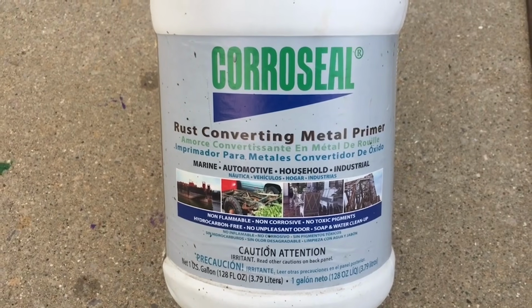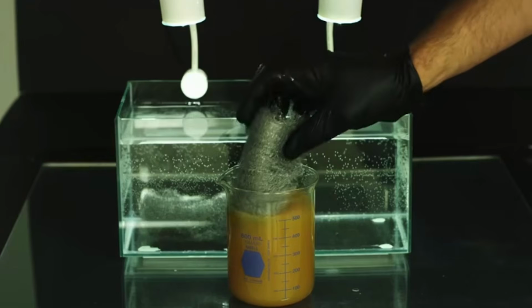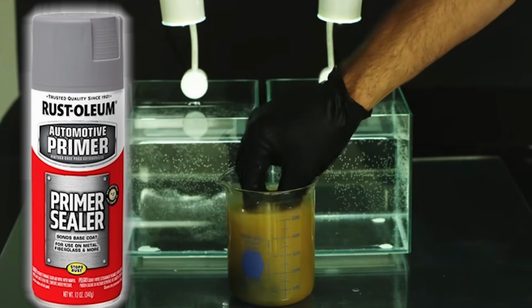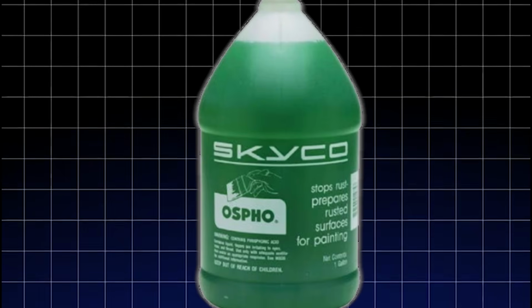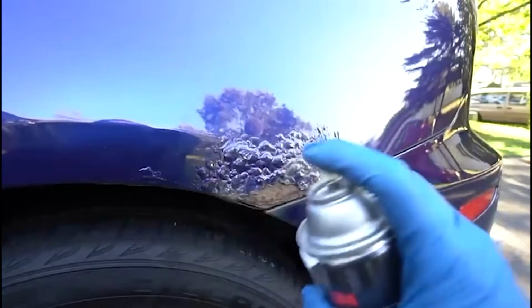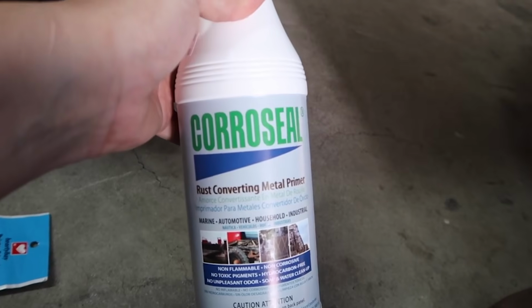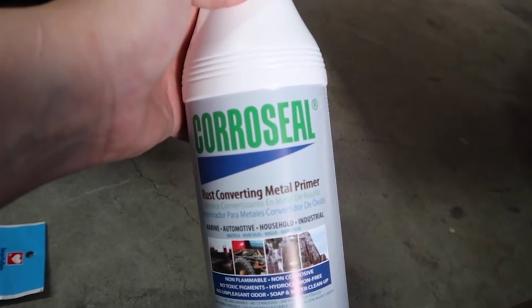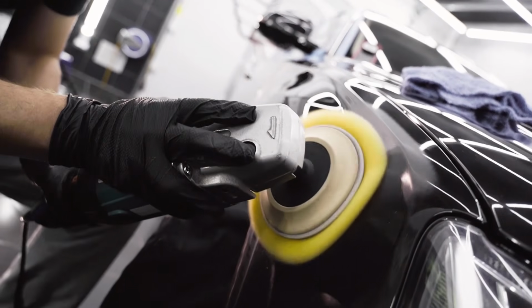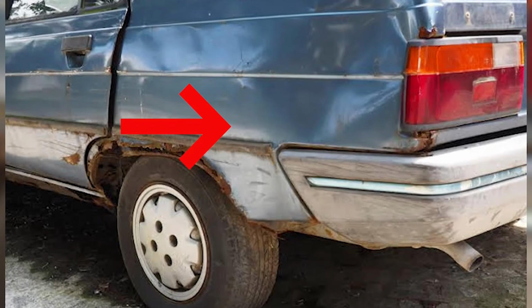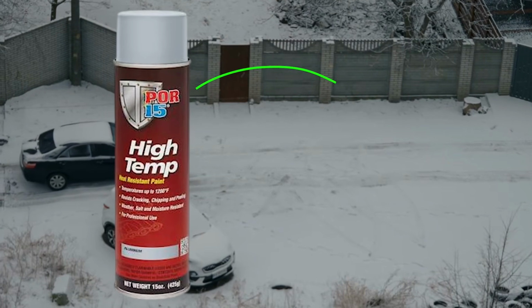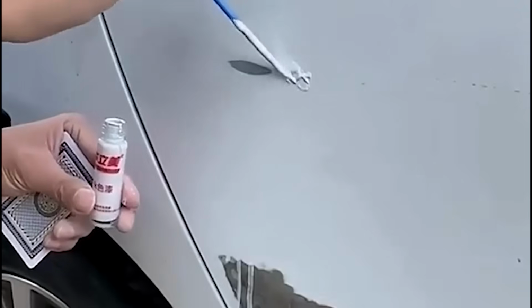It is a water-based formula that combines phosphoric acid conversion chemistry with a latex primer system in a single application. The combined chemistry means the acid conversion and the sealing primer are applied simultaneously rather than as separate steps, requiring neutralization between them. This eliminates the practical complications that make Ospho and similar high-concentration acid products difficult to use correctly on installed frame steel. The latex primer component thickens the formula enough to maintain contact time on vertical surfaces, while the phosphoric acid component is thin enough to penetrate into moderate pit surfaces. In our testing on moderate frame rust with early pitting, Corroseal produced genuine conversion into pit surfaces that the gel products had failed to reach.